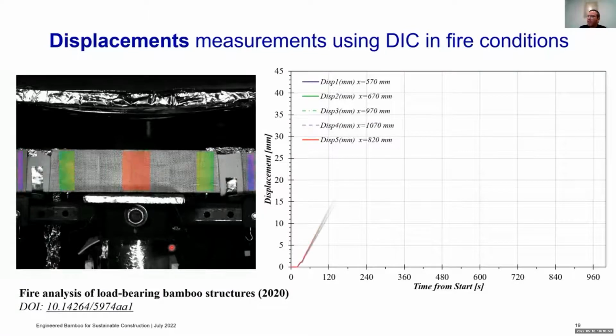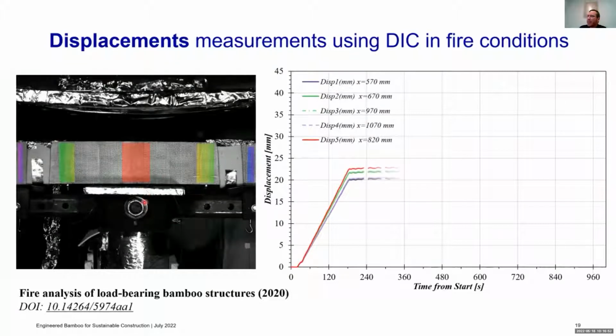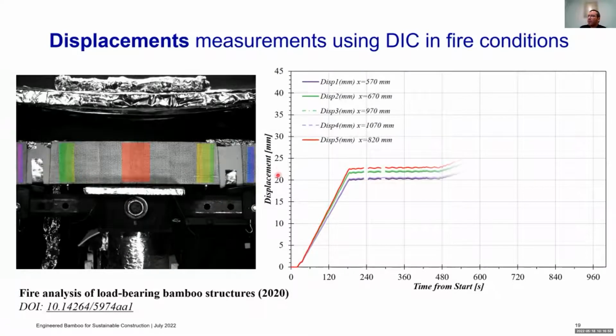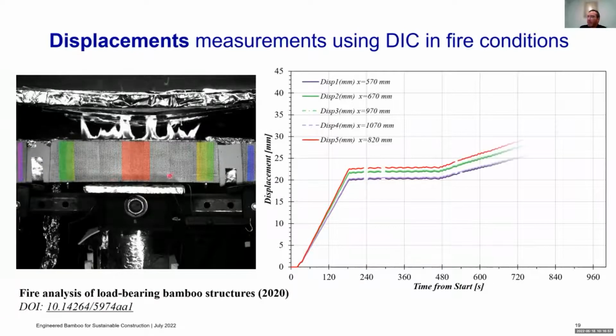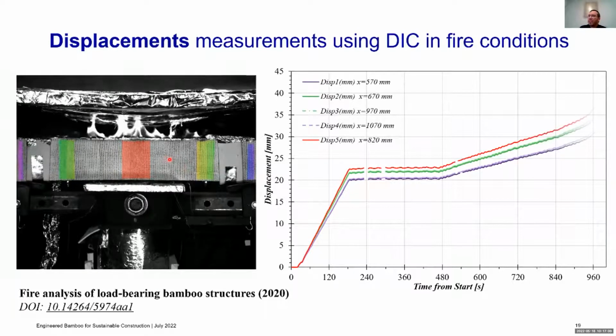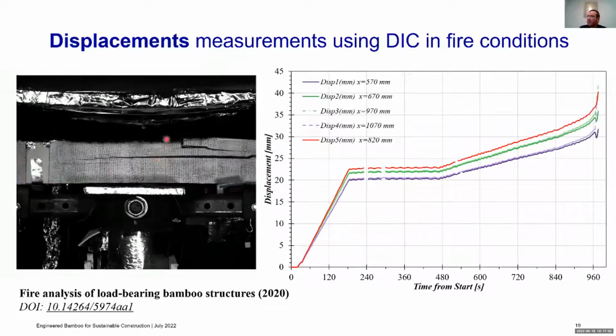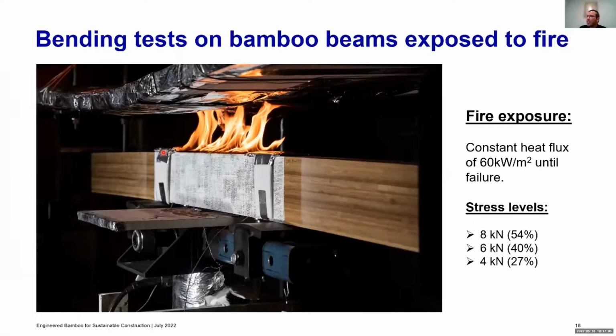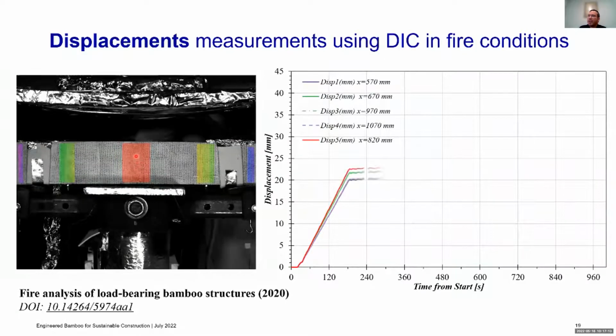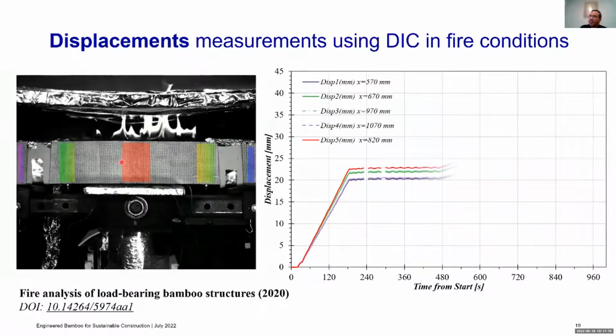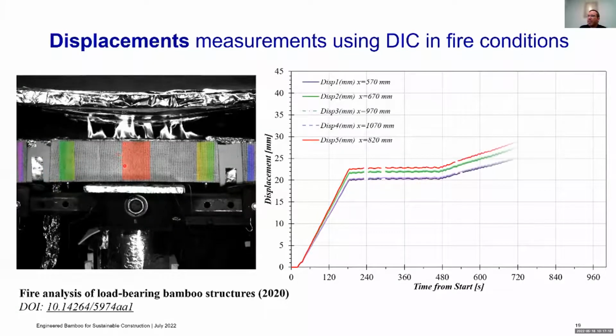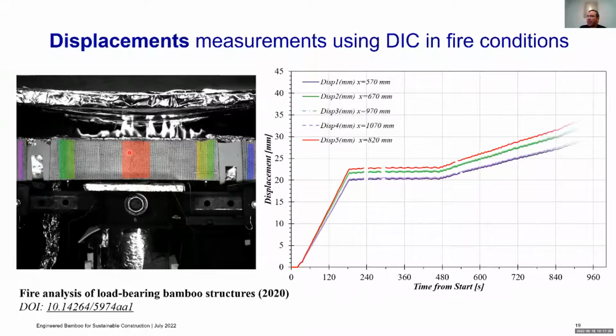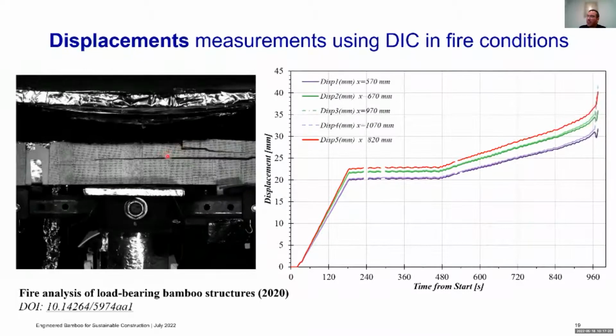And this is a video that shows how we applied the load and bent the specimen. The specimen was subjected to a constant load, and then we start burning the element until we reach the failure. So if I repeat this video, you can see that we bend the sample until the stress level that we defined. We left it at that constant load. Then we start burning the sample, and you can see with this digital image correlation that you can pretty much track the areas where the material is going to fail.